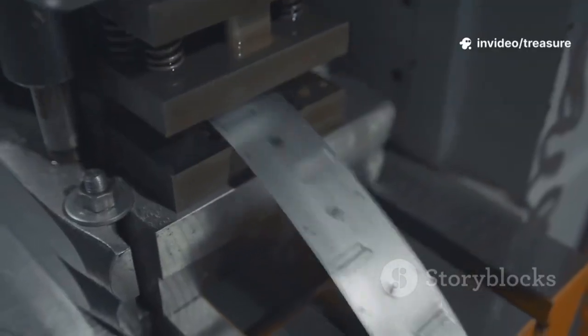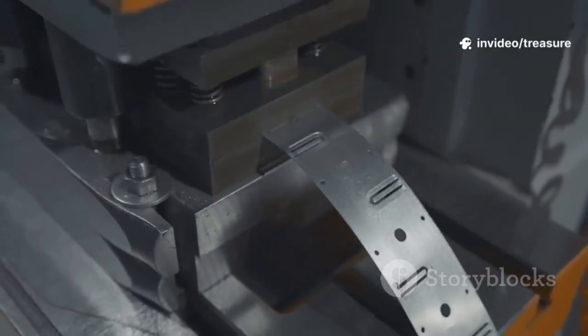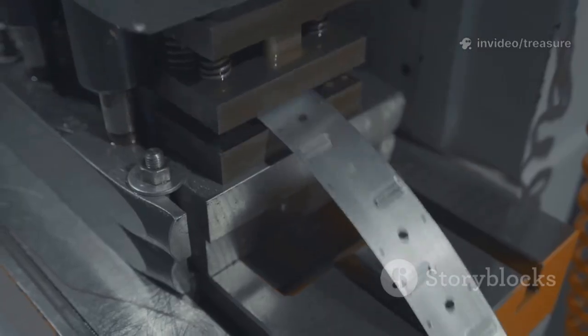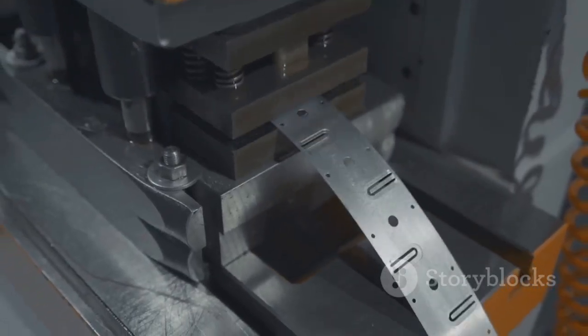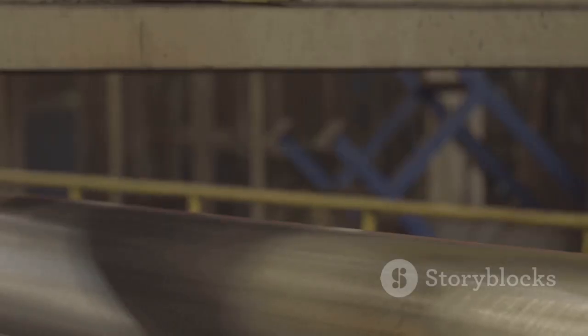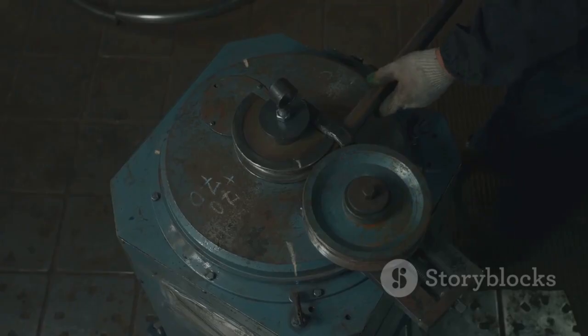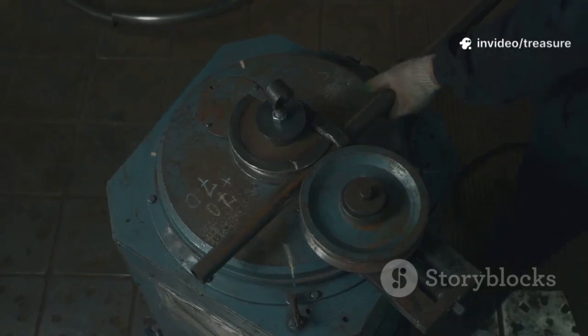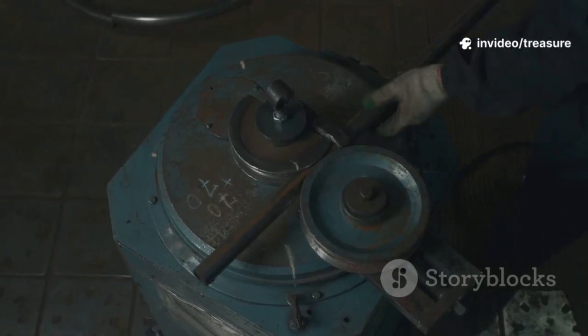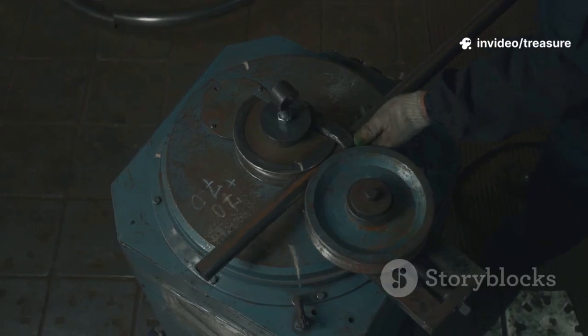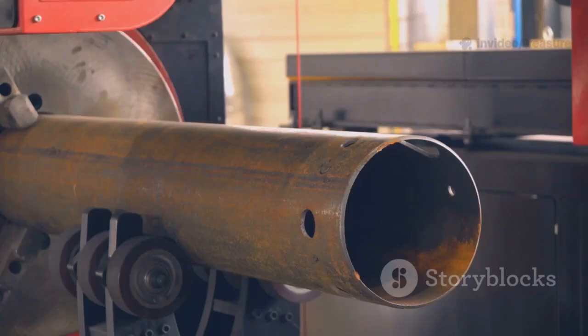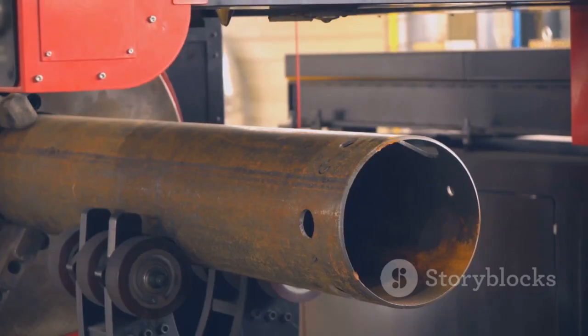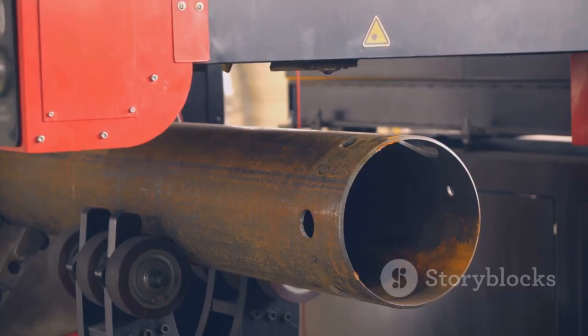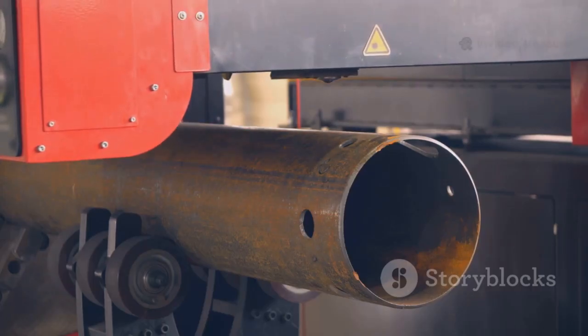Just as this cavity starts to form, a hardened, pointed tool called a piercer point or mandrel is pushed into the center of the billet from behind. The billet is literally forced over this point. It's an act of incredible brute force, as the machine simultaneously squeezes the outside of the billet with the rolls, while pushing a hole through its core with the mandrel. The result, emerging from the other side of the machine, is a thick-walled, rough-looking tube called a hollow shell.